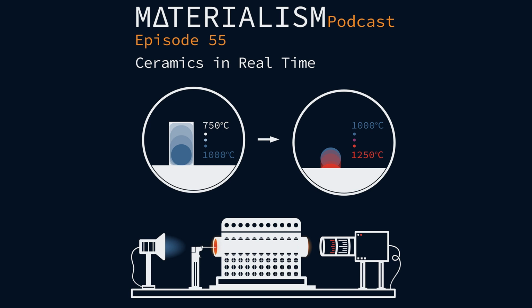So I could definitely see the value in just being able to look at something and observe it directly. How do you put markings on it? Are these just features that are on the as prepared surface, or do you have to mark it with a speckle pattern or something? How does this work? You need to give a certain shape to the sample, but you don't need to put markings on. So basically what you need to provide is a clear focusing plane. So the samples are like trapezoids, okay? Where you have a sharp edge and you look at that sharp edge, because otherwise the focus is not good.